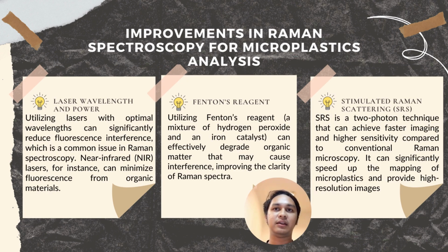Move on to the improvement of Raman spectroscopy for microplastic analysis. As we know, even though Raman has some advantages over Fourier transform infrared, which is FTIR, there are some disadvantages that might occur when using Raman spectroscopy. The main limitation is that the spectra have interference due to fluorescence. So there are three ways to overcome the interference. Firstly, we need to set up the laser wavelength and power. When we use the optimal wavelength, we can reduce the fluorescence interference by shifting the wavelength into the near infrared, so we can minimize the fluorescence from organic material.